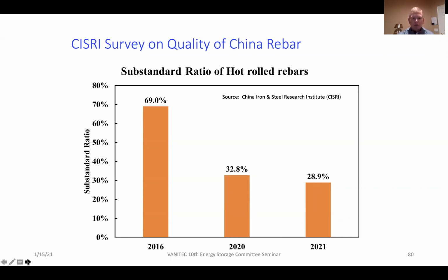And the reason the Chinese revised the rebar specification was to plug the loopholes that some of these people were going through, including using these quench and tempered steels. And you can see as time's gone on here, the amount of steel that's substandard, not actually beating the yield strength and elongation standards, has decreased, but we still have about 30% of the steel out there that's not meeting the specs, and most likely that's a result of not putting vanadium in that steel. So this chart just kind of shows there is some headspace in terms of vanadium consumption in rebar, even if the rebar production levels remain stable or below historical levels.